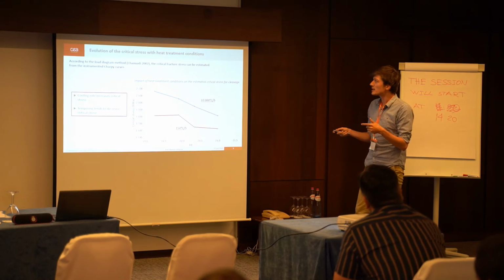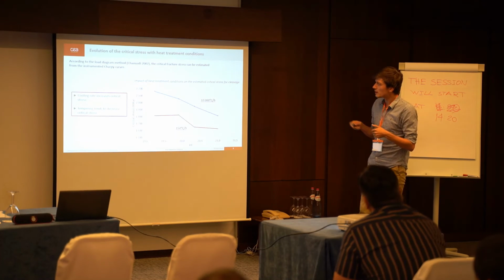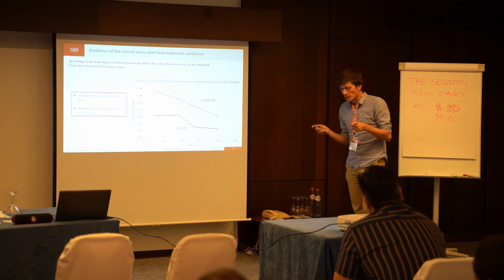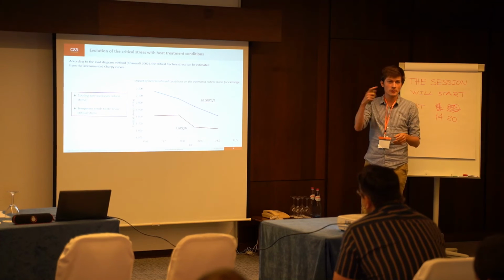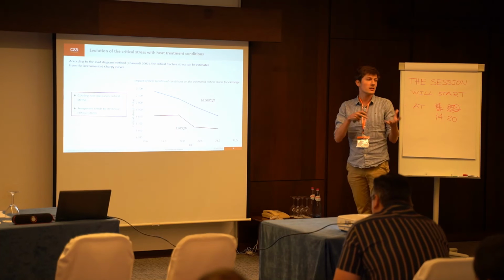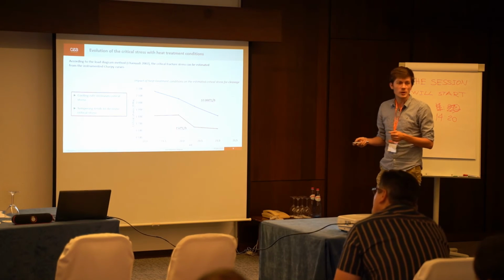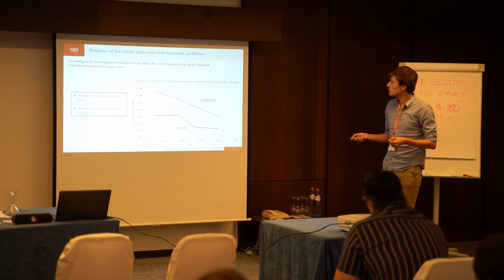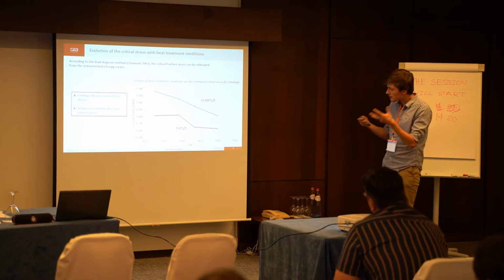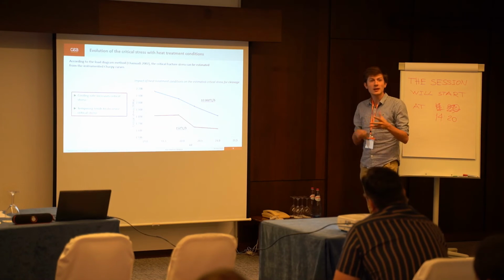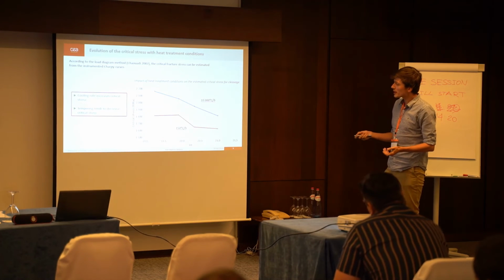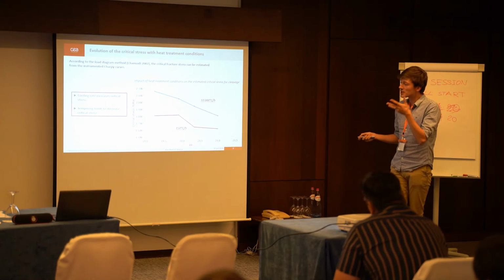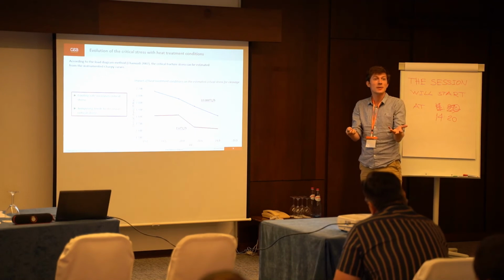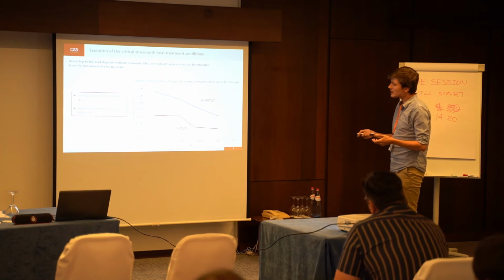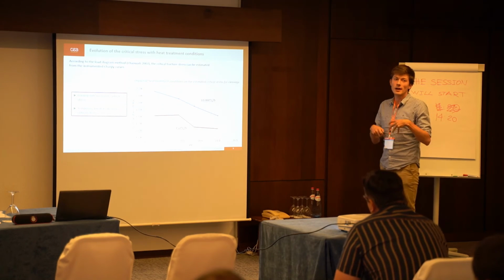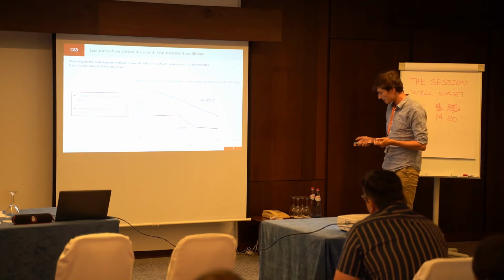So we tried to estimate the critical fracture stress. It's based on the load diagram method by Chapuliot. Using the instrumented curve, you can derive, as an estimation of course, the critical fracture stress for brittle fracture. You have the results on the graph here, and we found approximately the same thing as for the ductile to brittle transition. The cooling rate increases the critical stress, so it increases the impact toughness properties, and the temperings tend to decrease the critical stress, so they have a negative impact on the impact toughness properties.